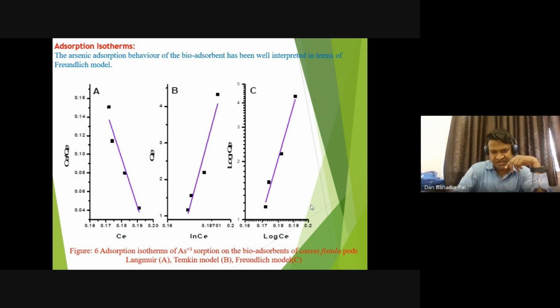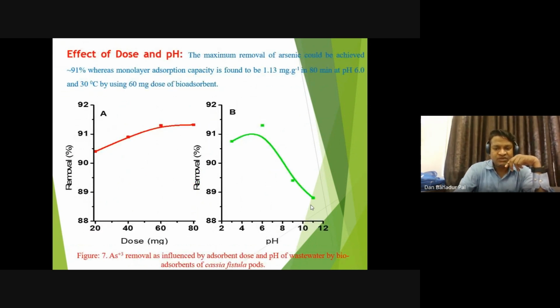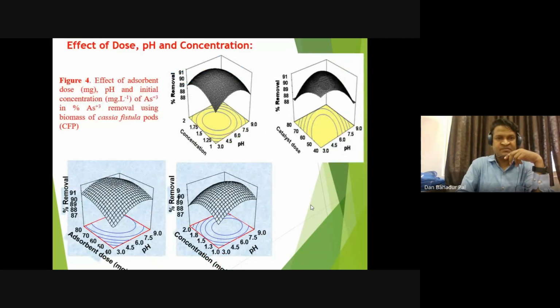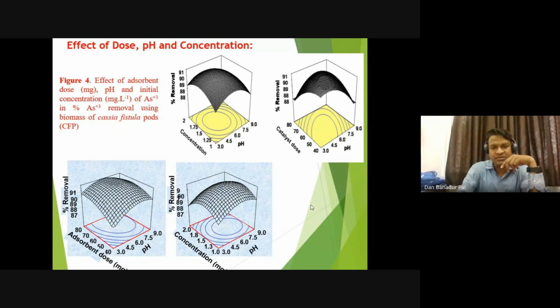Next, we go for the adsorption isotherm. Here also we have chosen three models, Langmuir, Freundlich and Temkin, but in this case the Freundlich model is suited because the R square value is higher. Then we see the effect of dose, pH and concentration on the adsorption of arsenic. The dose is optimized: 60 milligram gave the best removal of arsenic 3. Similarly, the pH is 6; at pH 6, the acidic region, removal is better. The optimization shows a similar effect of dose, pH and concentration.